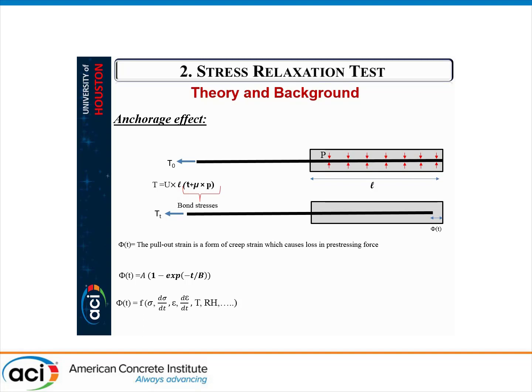Another important factor is to consider the effect of anchorage losses on the total relaxation of the CFRP system. As you know, in post-tension application of CFRP tendon, we have the anchorage at the end of the CFRP as a permanent element. So due to time, by introducing the stresses, the CFRP starts to pull out, and this pull out or progressive slippage of the CFRP inside the anchor can be another source of loss in the system.